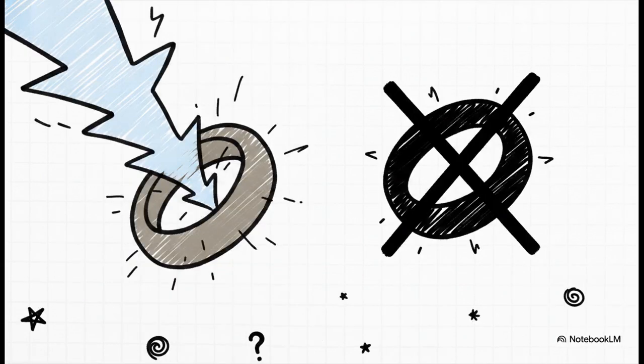But here's the catch, and it's a crucial point about the physics of thin film interference. It has hard limitations. Because the color relies on light waves bouncing and interfering rather than actual pigmentation, true black is physically impossible to achieve this way. Thin film interference simply cannot absorb all visible wavelengths of light. If you push the voltage way past 110, the layer just gets too thick and the interference effect completely degrades into this muddy gray-brown color.